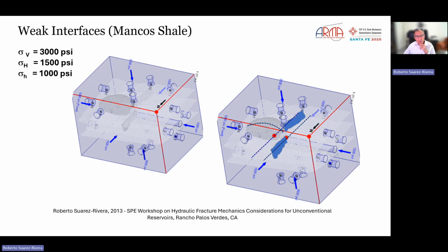The second surprise was that the fractures that happened through these perforations were avoiding each other, which is okay. We understood that. One fracture happens, it creates a stress shadow, and therefore the other location is not the preferential one, so the other fracture happens in the opposite direction. So there are half-wing fractures occurring, avoiding each other. That's fine. The problem is that they were perfectly contained, even though the stress that we are applying on this face of the block is uniform. One would anticipate a penny-shaped fracture across the entire cross-section of the block, and yet they're fully contained.